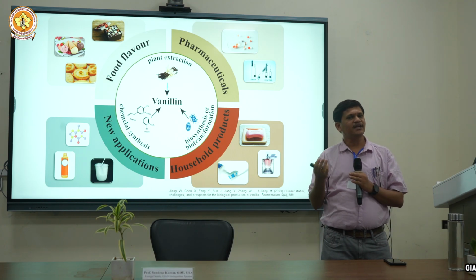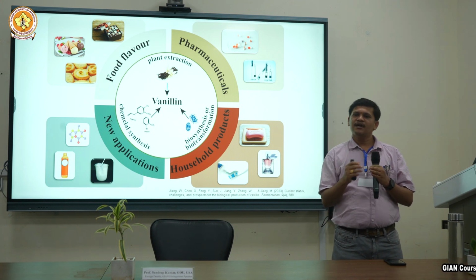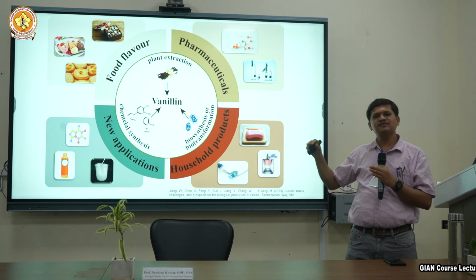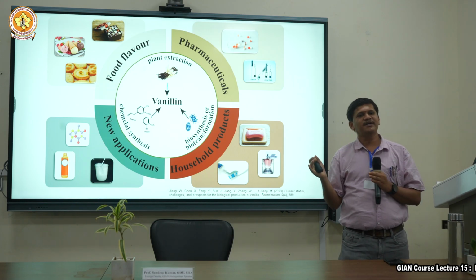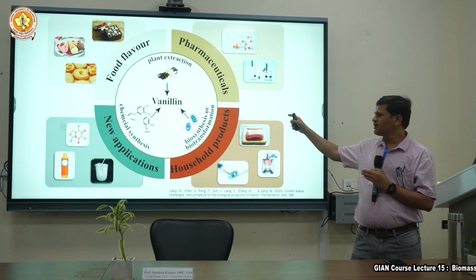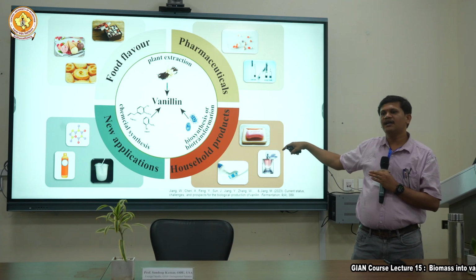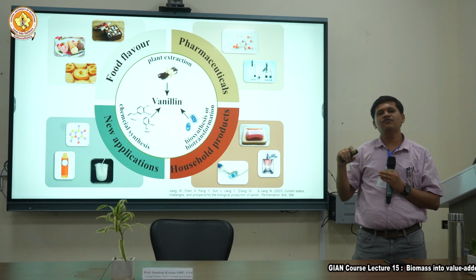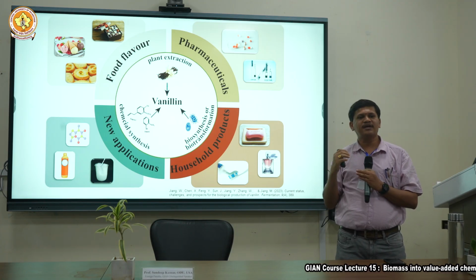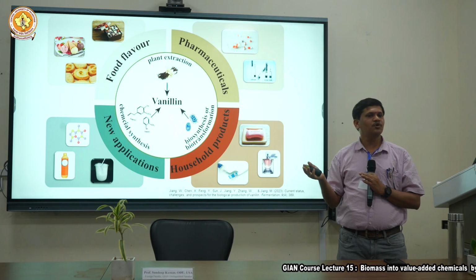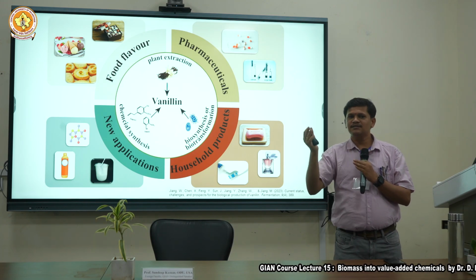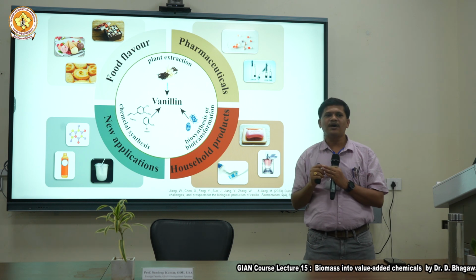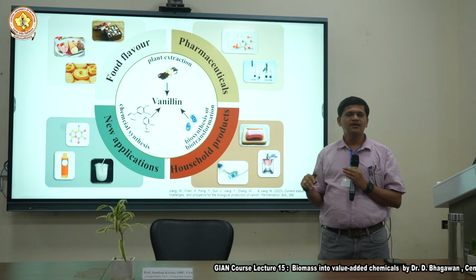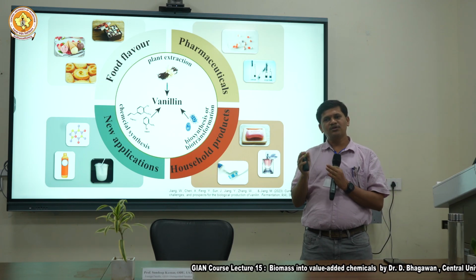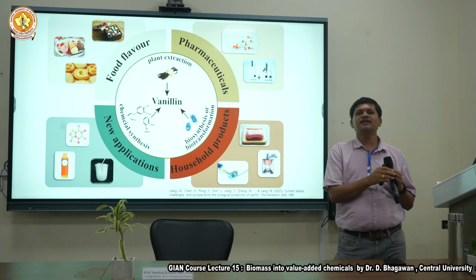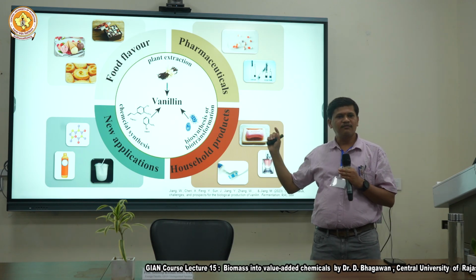Again, with purification we can get a 99% pure compound, but it still has some designing or developmental aspects where we can enhance the production, because here the conversion rate is 99%, but we are yielding only 70%, meaning 30% loss still. If we control that 30%, then we can yield a good amount of the pure compound. When we enhance the concentration of this particular selective compound, obviously the impurities will get reduced, right? That is one of the good things, where we can convert the whole lignin, which we consider as waste, into value added chemical compound.